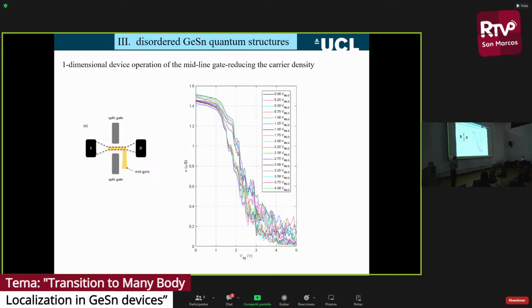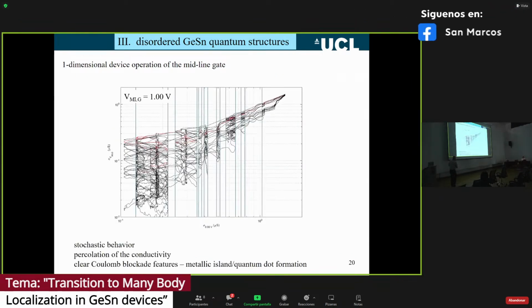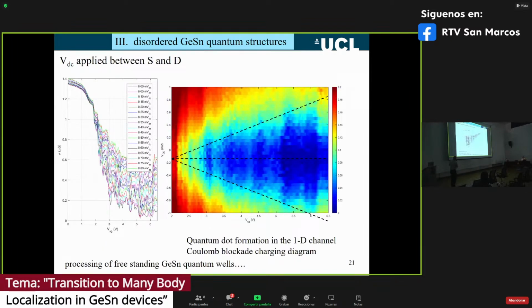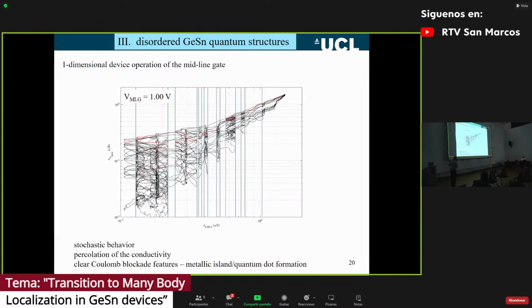But if we replot this set of data in a more systematic way, what I've plotted now is the device conductance on the y-axis. It's on a log scale, just to expand what's going on at low signal levels, as a function of the conductance at 0 midline gate voltage. So the first set of data will be just a straight line. As we apply a midline gate voltage, we see very, very clear Coulomb blockade oscillations here. So we've got this condition for Coulomb blockade, which means the current through the system can only change when it meets the condition for a Coulomb blockade. And it's very, very clear in this system where this occurs.